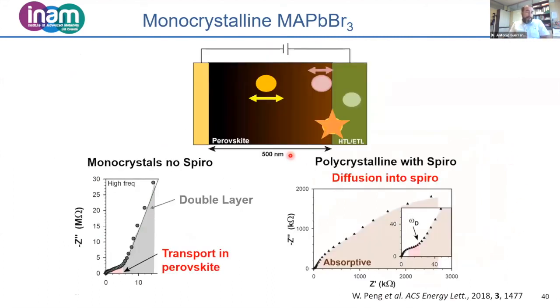Okay, the response always depends on the device that you've got. So this is one of the reasons why it's so hard to propose a general equivalent circuit. If we add a spiro layer at the end of the perovskite, now we don't see the accumulation of ions anymore. We still see what looks like a 45-degree angle line, but now we see this arc. And this is a typical absorptive impedance when we have ions that are crossing one layer.